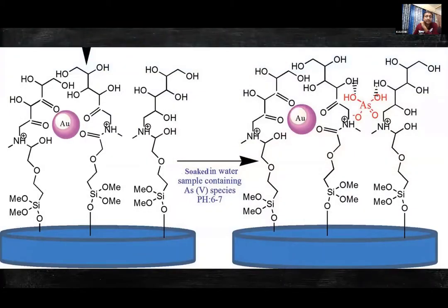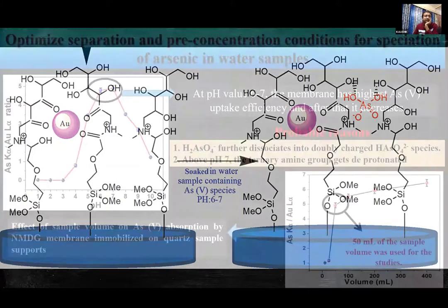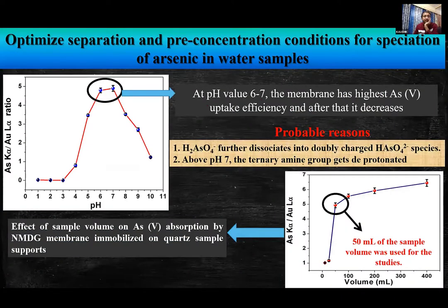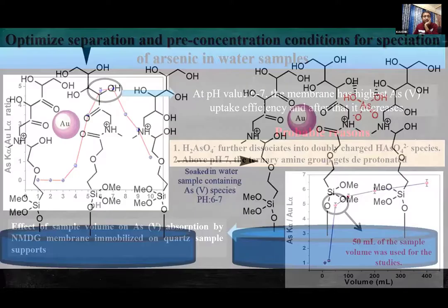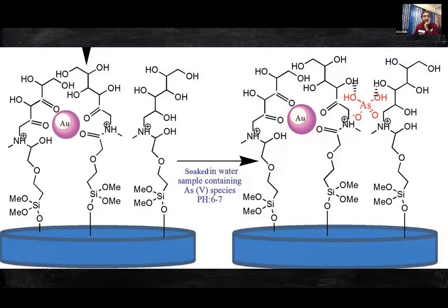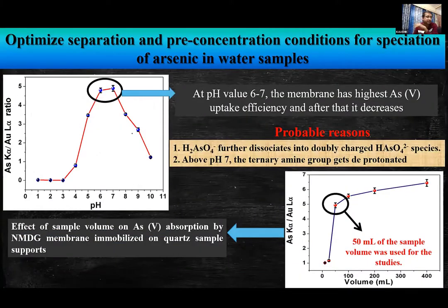Now, in this picture, you can see that in this NMDG membrane, the arsenic 5 species basically attach via electrostatic interaction. There is a tertiary amine which has a positive charge, and this arsenate has a negative charge. So this electrostatic interaction binds the arsenic 5 species. But what happens after pH 7 is that this tertiary amine gets deprotonated. As there is no positive charge, after pH 7 these electrostatic interactions steadily decrease, which reduces the arsenic 5 uptake efficiency. So you can see after pH 7, the ratio of arsenic K alpha by gold L alpha steadily decreases.